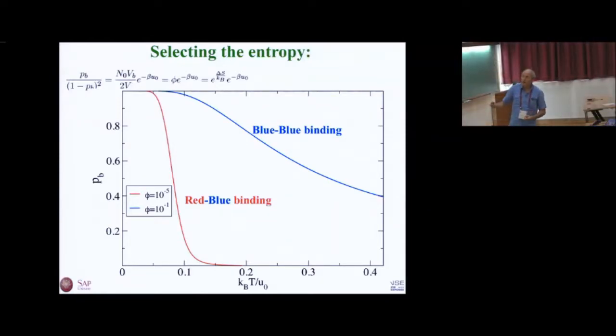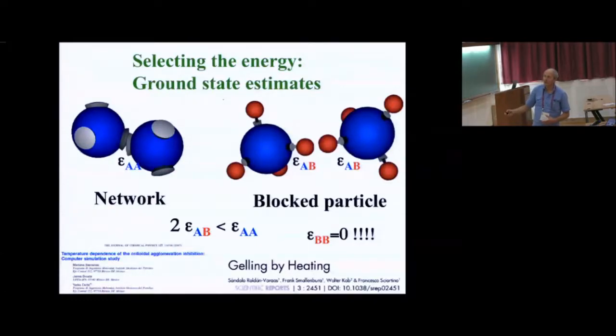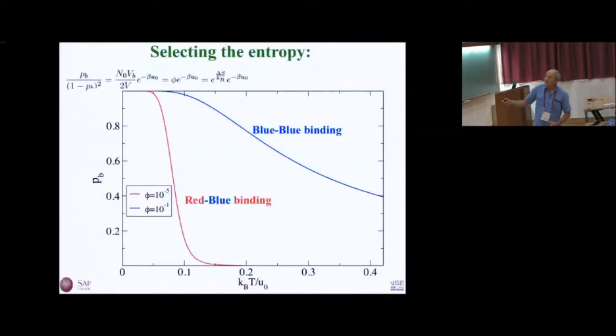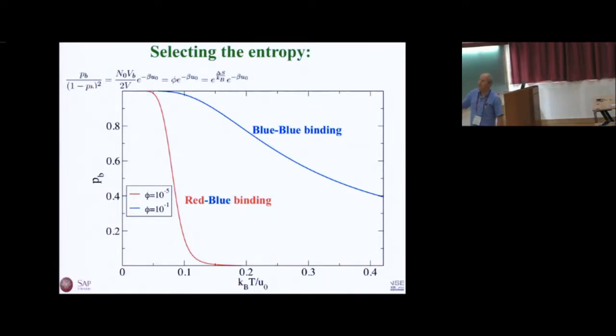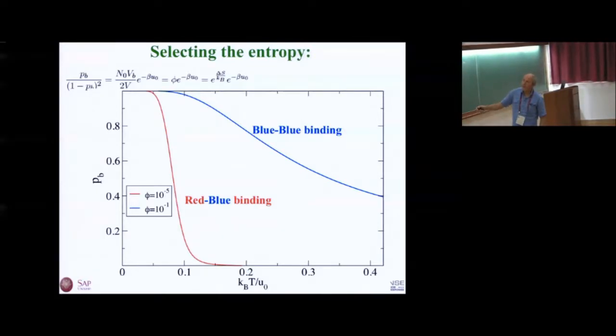Now, if you remember my last lecture, if I have two particles which bind to each other, we have derived this expression, and we have seen that the bond probability, the probability to form a bond between these two particles, is related to an entropic term, which is the ratio of the bonding volume to the total volume, and an energetic term, which is the energy scale of the bond. So this energy we have fixed already, by this inequality over here. Now we can fix this entropy, and make sure that we have the blue-blue binding like here, and then the red-blue binding at a much lower temperature and much sharper, right?